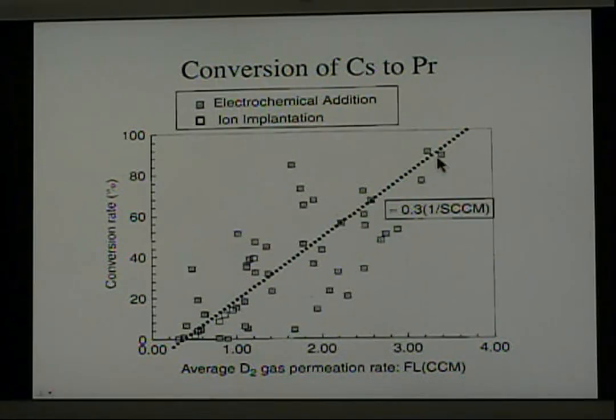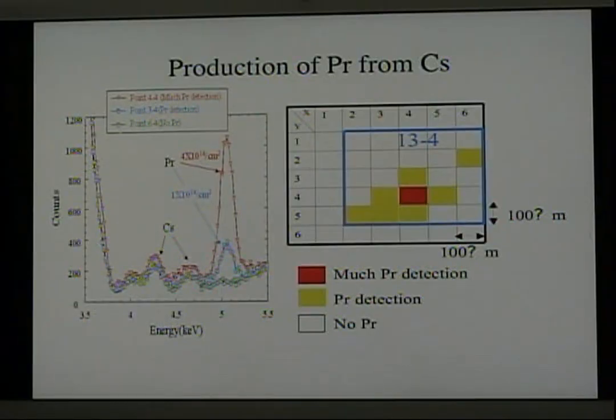You notice that there's quite a bit of scatter when you look at the material that's been electrochemically added to the surface, but when ion implantation was used, the scatter is much reduced, but the same effect is seen. A sample of this palladium after the conversion process is then looked at with an X-ray beam that has a very small cross-section of only 100 microns. And you can see the detail that they get in analyzing for the praseodymium using this technique.